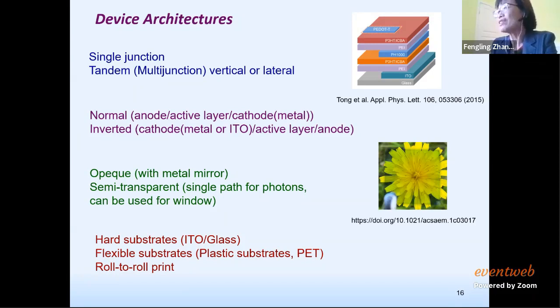They can be normal or inverted. This depends on whether the electron is collected on the bottom or on the top. If on the bottom, we call it inverted. If electron is collected on the top, we call it normal. For the transparency, they can be opaque if we have the metal electrode. We also can make it semi-transparent, then we need to change the electrode. Both electrodes should be transparent to allow the light to pass through. The substrate can be hard, on glass, also can be soft, on plastic, like the most common is PET. So that's possible to make the device by printing, roll-to-roll.